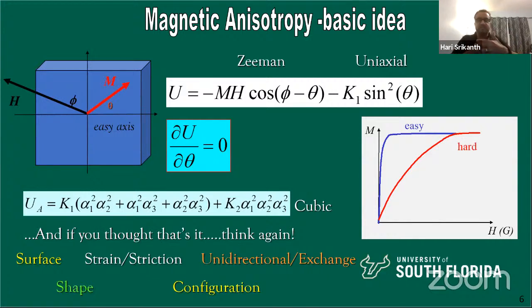If you have an interface between an antiferromagnet and a ferromagnet, it turns out that because of the differential anisotropy at the interface between these two magnetic phases, the interfacial spins are pinned. And so you can have very interesting consequences in the sense that the coercivity of the hysteresis loop can increase, and also the loop itself can shift. This is known as the exchange bias. You can actually have the bias field, which is determined by the shift in the hysteresis loop. So that's an important contribution of interfacial anisotropy in playing around with the hysteresis loops.